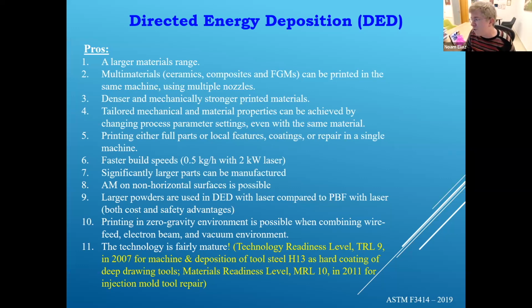So basically, if I compare to powder bed fusion, the DED has a larger materials range. You will see a table later. You can print multi-materials, this is a great advantage, from composites to functionally graded materials, in the same machine, using multiple nozzles. For instance, at Tel Aviv University, I have 4 different nozzles, so I can print simultaneously 4 different materials. They are typically denser and mechanically stronger compared to powder bed fusion. Typically, there are, of course, some special cases where it doesn't happen.